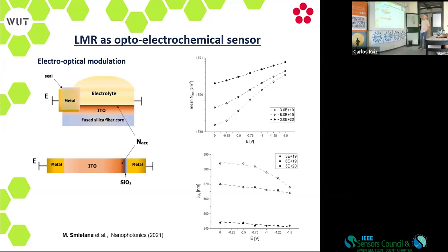And when a negative potential is applied, we form here an accumulation zone. And when the accumulation zone is formed, the refractive index of this region drops. But it drops differently for different accumulation of the free charges in the material. So when we obtain a certain material, we need to take care of the number of charges that are there. For electronics, definitely a high number of charges. But for optics, unfortunately, low.